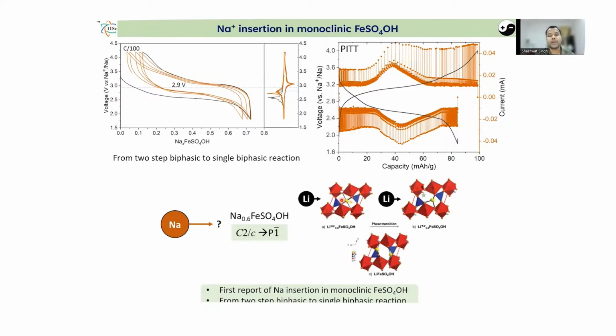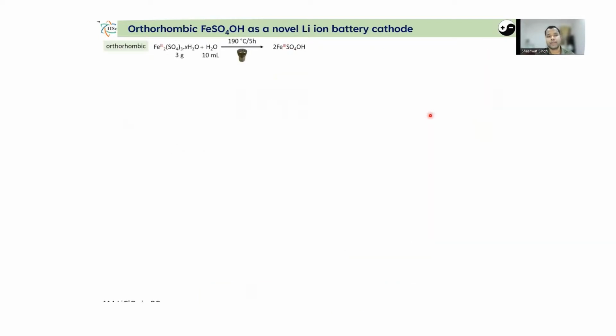And why that happens is because lithium can be stable in both octahedral as well as tetrahedral environments, whereas sodium would only like to be stable in an octahedral environment. Therefore, when sodium goes and sits in these kinds of tunnels, it cannot be accommodated as it was for lithium, and therefore we only see one step of the reaction.